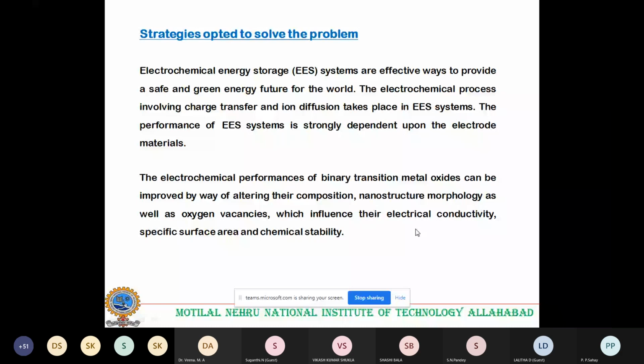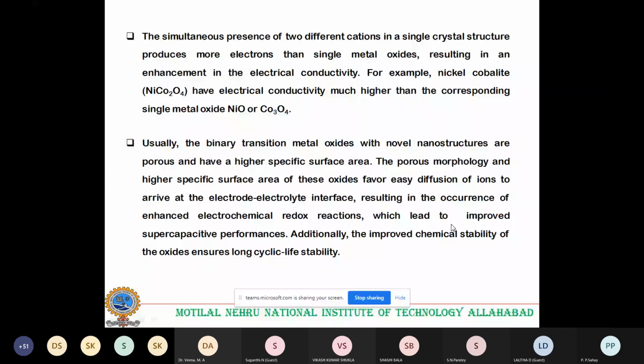The simultaneous presence of two different cations in a single crystal structure produces more electrons than a single metal oxide. For example, if you are using nickel oxide and cobalt oxide independently, their conductivity will be less compared to the nickel cobaltite, that is NiCo2O4. So with the binary metal oxide, it is possible that we can enhance the electrical conductivity of the film. This is the one.